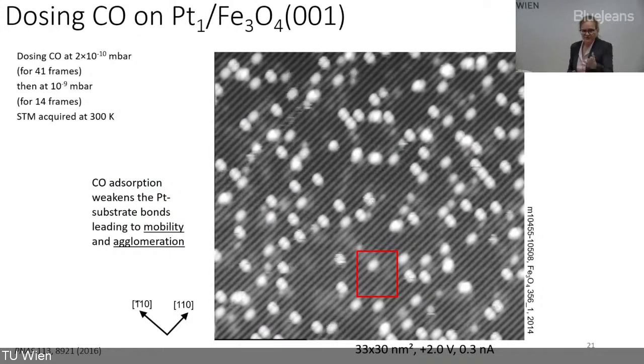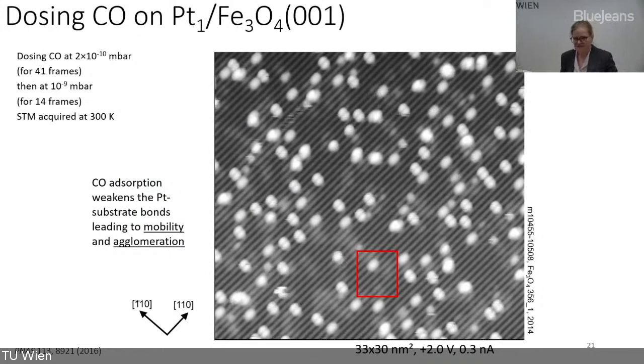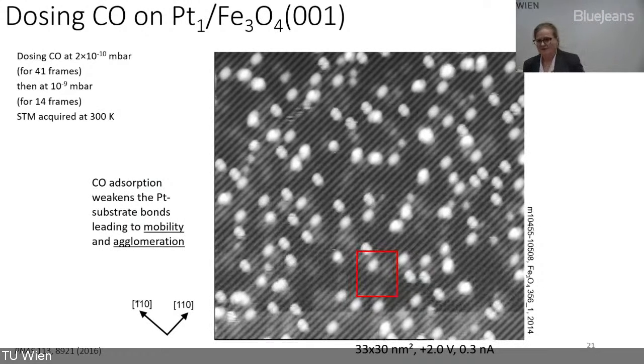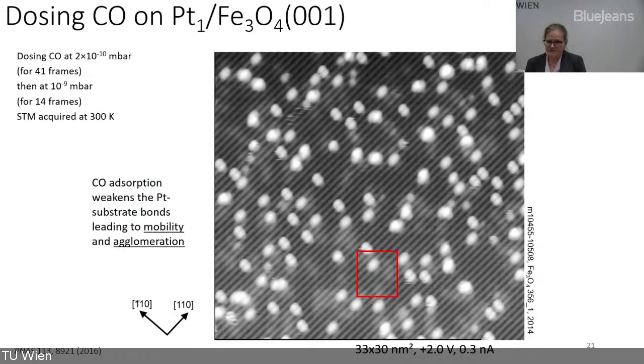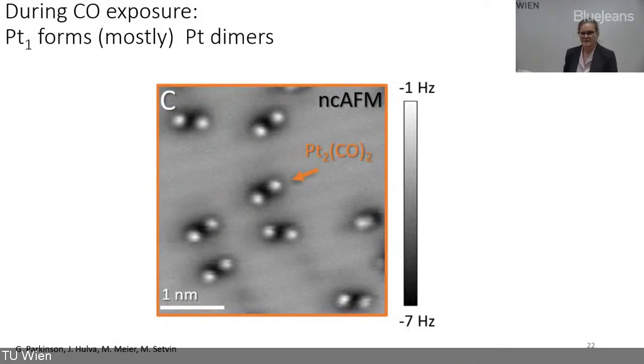Without seeing what happened, you would never have guessed that this is a platinum dimer. It turns out that if you put enough CO on the surface, most of these platinum atoms will not stay single atoms, they will come together and become these dimers. We can see them quite nicely with non-contact AFM.